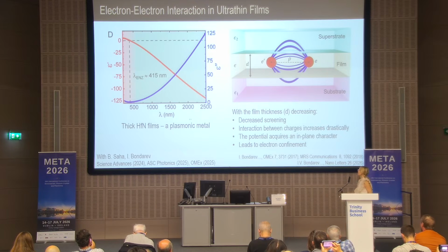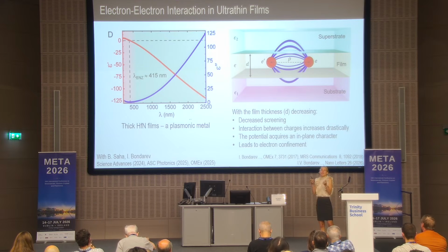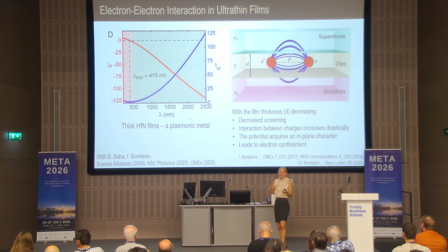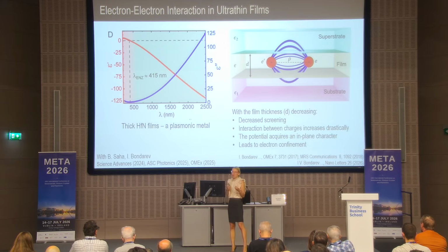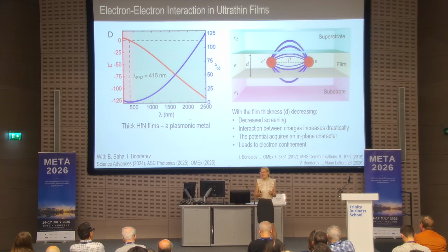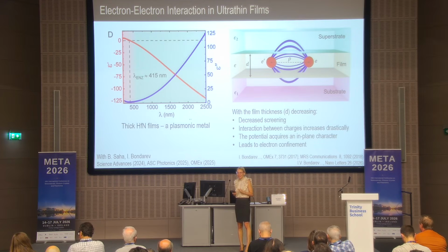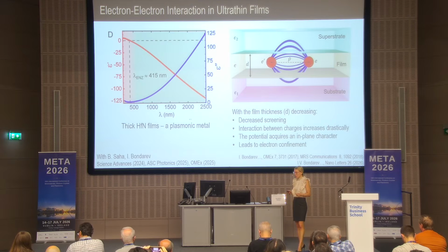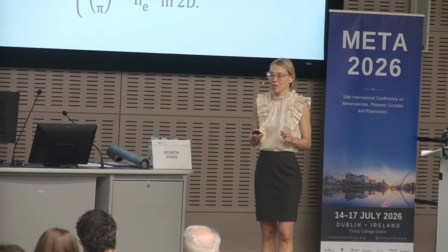What really happens here is that when the film thickness is decreasing, the electrons start to interact really strongly. So you really have decreased screening, and you start to feel each other through the substrate and superstrate. This increased interaction between charges can actually lead to very interesting things. You have strongly increased electron confinement. The potential would acquire almost in-plane character. But when those experiments were run on hafnium nitride in the ultra-thin regime, Igor Bondarev actually came up with